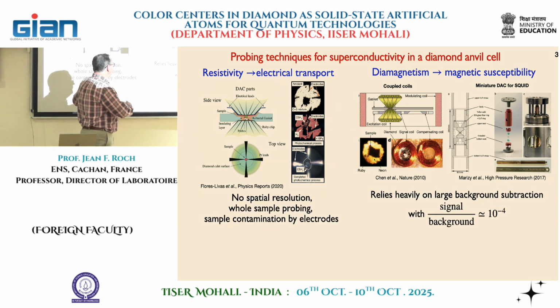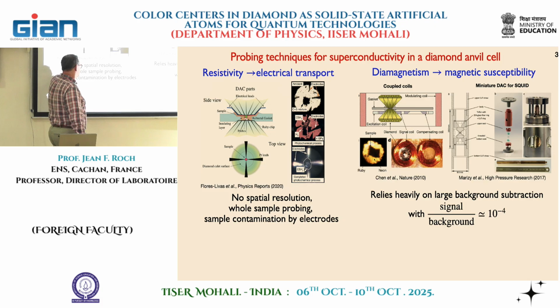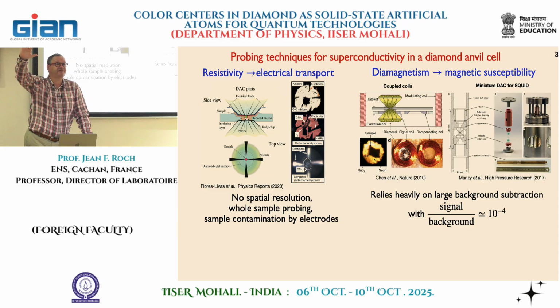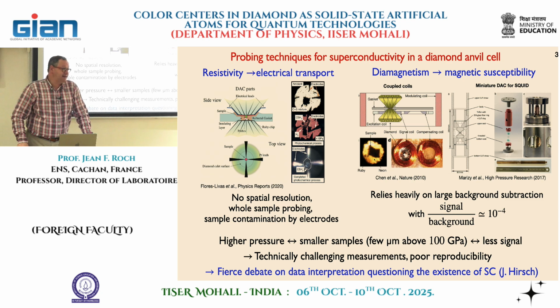So with all these techniques, you do not have any spatial resolution. You probe the whole sample. You can have sample contamination. And in all magnetic measurements, it relies on a large background subtraction. The signal over background is typically 10⁻⁴. So you want to see a negative magnetic response over something which is a background of 10⁴. And this is very, very challenging in the data analysis. So all that led to a fierce debate on data interpretation, even questioning the existence of superconductivity.